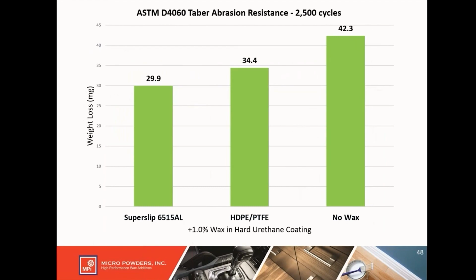We also can look at Taber abrasion resistance with this product. And in the middle, you can see a HDPE PTFE powder. These have been used for decades as among the most high-performance additives for things like abrasion resistance. But on the left, SuperSlip 6515 AL, PTFE-free, better than the PTFE-containing composite in the middle.